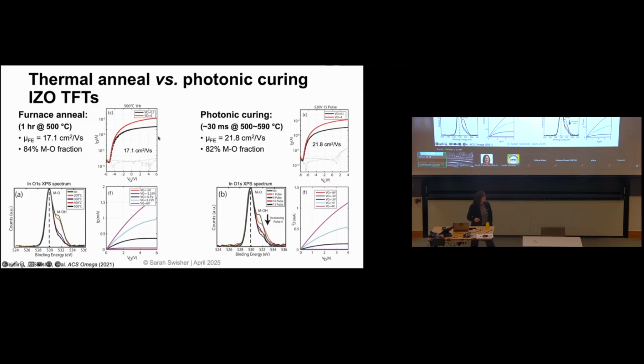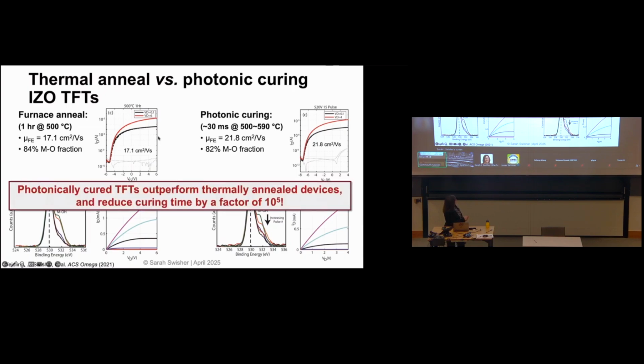And mobilities of about 20 are pretty decent. They are not record setting, but they are certainly on par with what people are seeing in these solution processed oxides. So they actually outperform our thermally annealed devices, and they do that while reducing the curing time by about 5 orders of magnitude. So this is super exciting, but right now, these devices are still on glass. We have made transistors on plastic as well. There are other challenges that we're dealing with those. The performance is lower. We get mobilities of about 4 instead of mobilities of 20, but we're still working on that part.